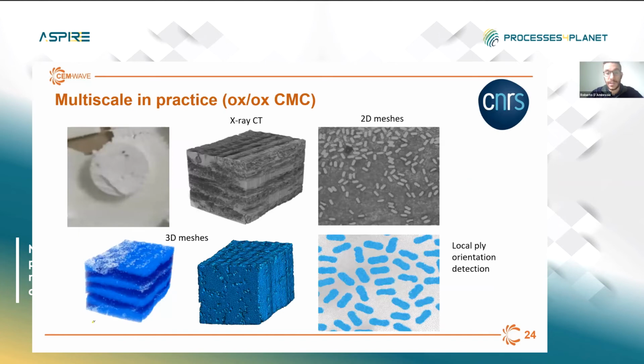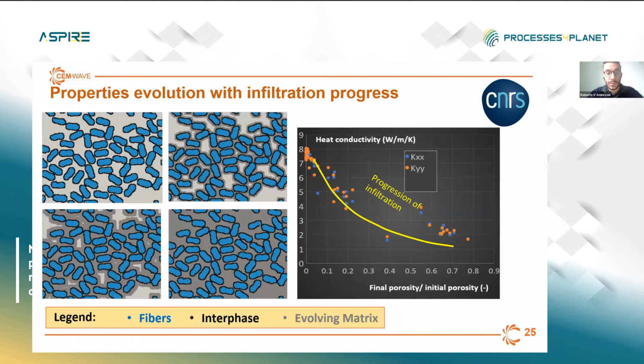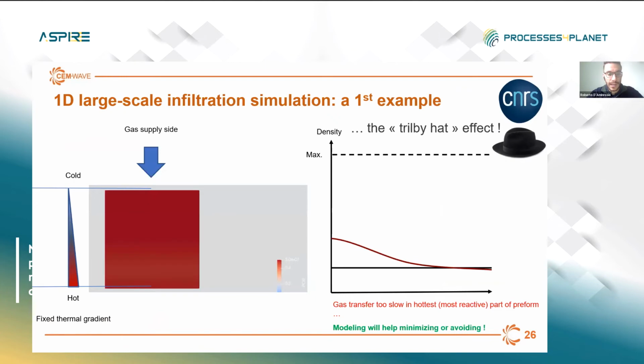So the first task dealt with the collection of a series of image data coming from X-ray computerized tomographic scans and SEM micrographs, which have been then processed by specific tools in order to detect the precise fiber reinforcement architecture. So once obtained our elementary computational domains, the physical properties have been determined in order to retrieve the effective bundle coefficients as a function of the local fiber density and infiltration degree. Here, I wanted to show you first results from macroscale simulations, which shows the porosity evolution when applied a fixed thermal gradient in this case, which is a quite simple one-dimensional case representing a single pore channel.